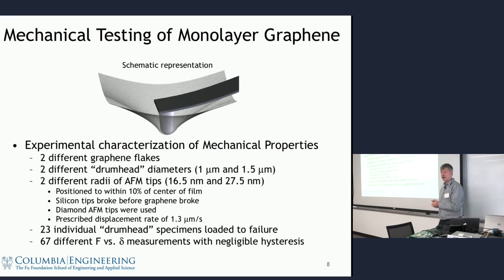Well, it turns out no. So it turns out we kept doing these indentation experiments, and we knew we had to understand the radius of curvature of the tip to see how sharp it is. And so we would look at it in a TEM before and after, and we would always find that the tip was broken after our indentation experiment.